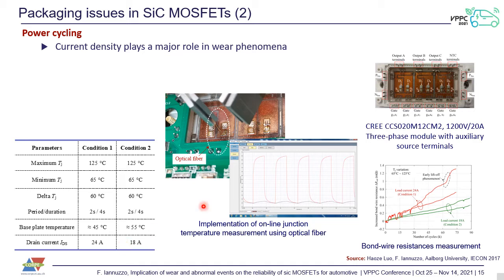A detail of the inside of the module under test is depicted here on the top right hand side of this slide, and some experimental results are shown here. As you can see, what we obtained is an obvious difference in the behavior of the 24 amperes case compared to the 18 amperes. Everything else was the same, so this difference in behavior can only be related to the higher current density through the bond wires, which, as I mentioned before, is a rather critical parameter when it comes to reduced area silicon carbide chips.